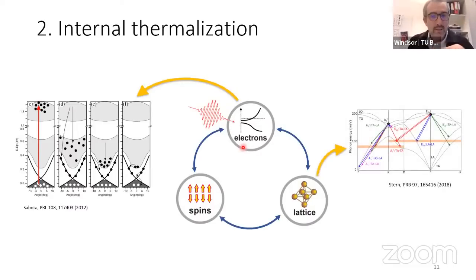The same can be said about the lattice and the spins. I'm only going to talk about the lattice here because I think other people can say more about the spins. But the concept is similar. Here we have the phonon dispersion of graphite from this nice paper over here. And the same thing is sort of described. Here we have an initially excited phonon population up here, and through a series of phonon-phonon scattering events, this initially highly preferential occupation of high energy optical phonons evolves to lower energy phonons and eventually to a new thermal state that's characterized by a higher temperature than the temperature we started with.